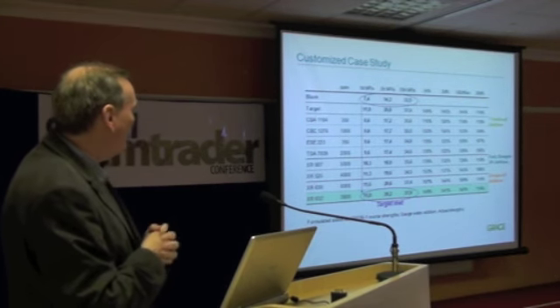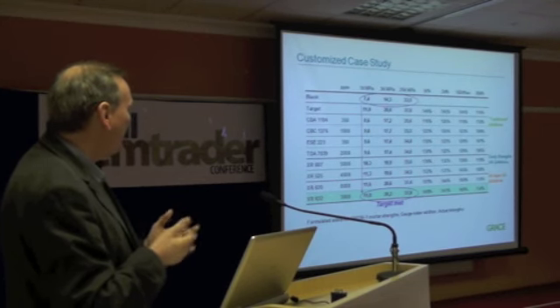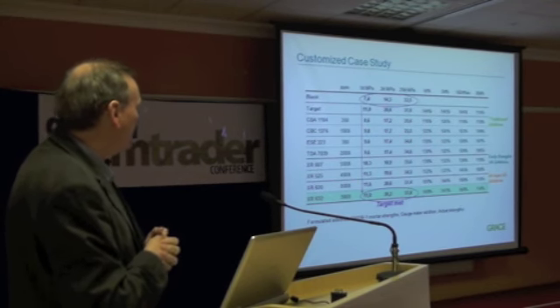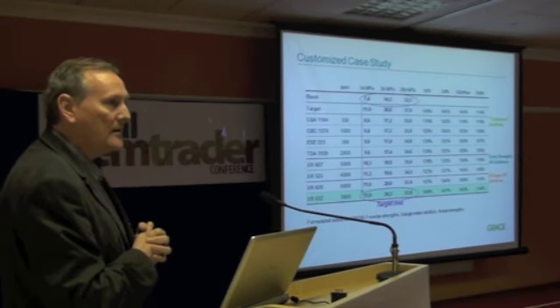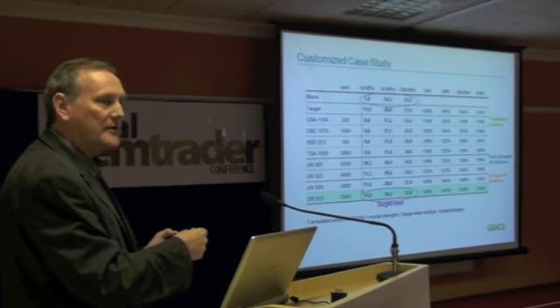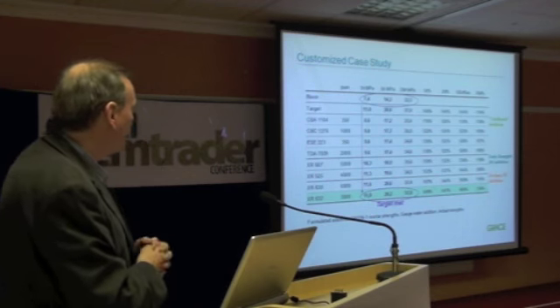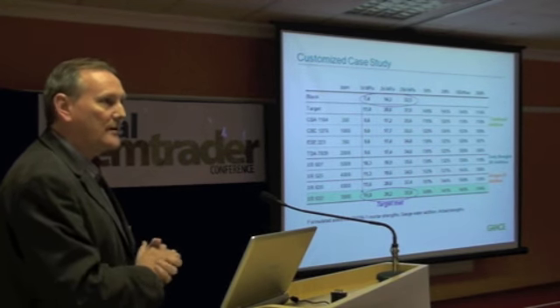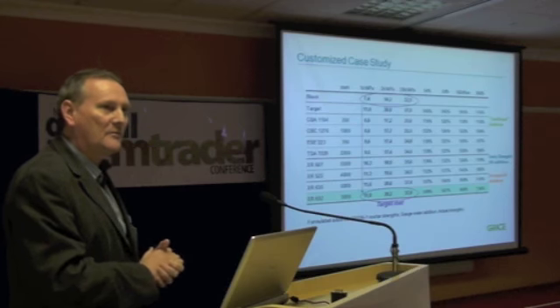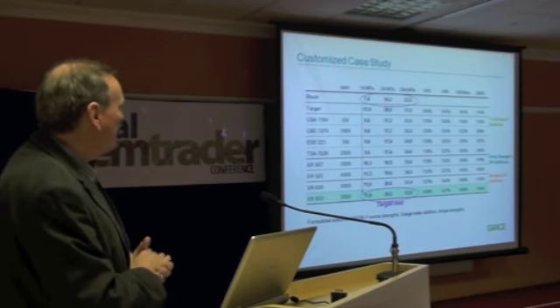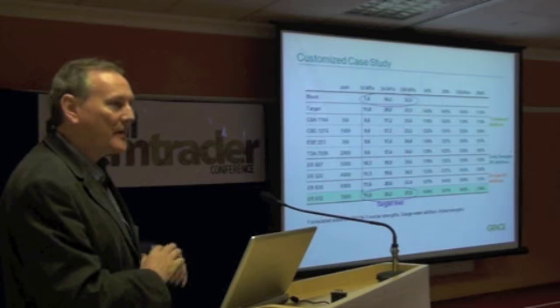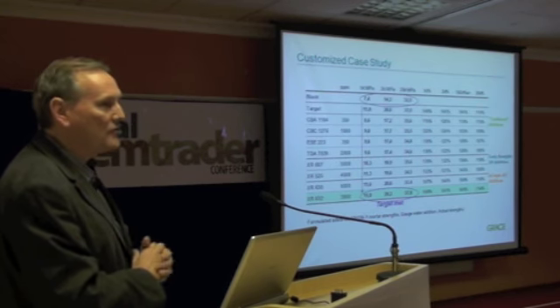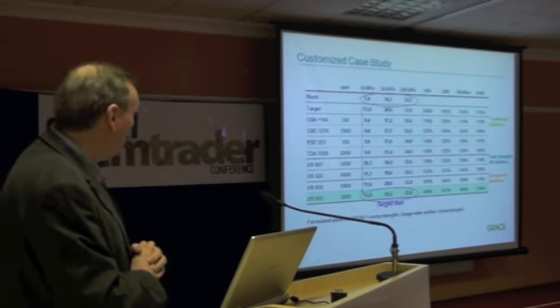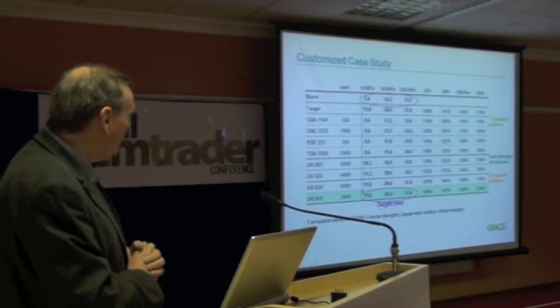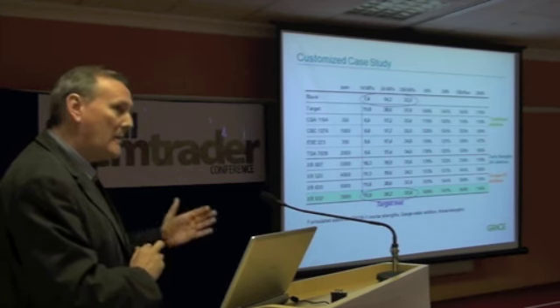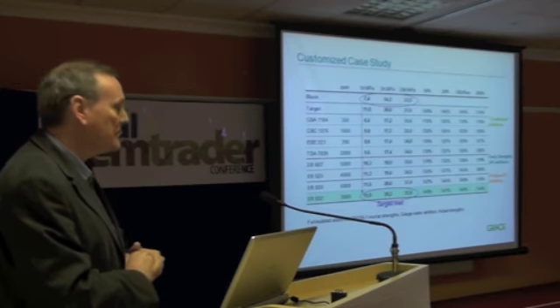The first used a higher alkanolamine technology that we patented about 20 years ago. The ESE is a modified alkanolamine that we work with one of the major chemical producers to synthesize, and the TDA is a very traditional old one, using common chemicals. And they more or less did what we expect them to do. Some of them gave good early strength, some of them gave good late strength, but none of them could reach the targets. And then the next XR607 and 525 are coming out of the second phase of the customization.